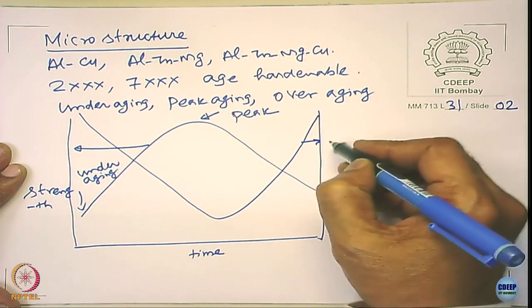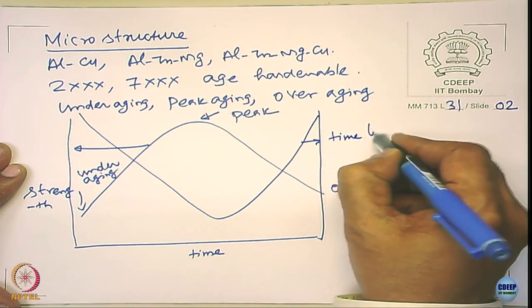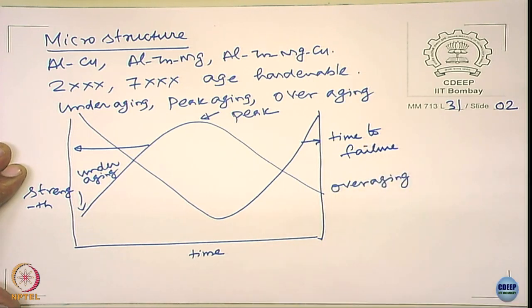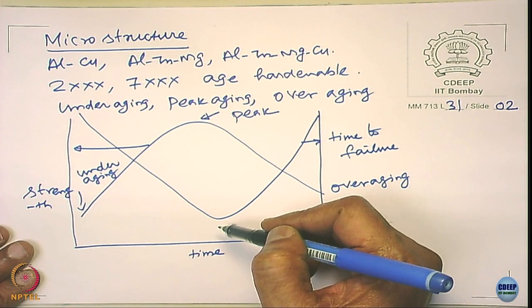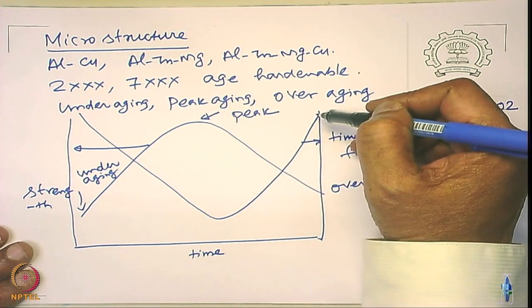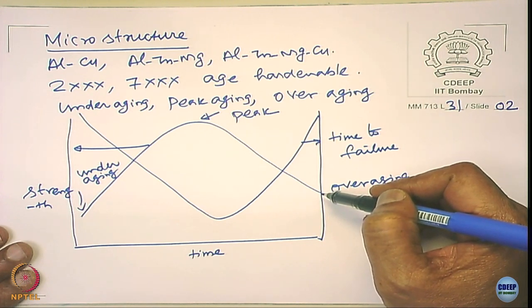At the peak-aged condition, the alloy becomes most susceptible to SCC. When you do over-ageing, the SCC resistance increases. So when you increase SCC resistance by over-ageing, you have a drop in strength level. There is some compromise on the available strength for structural applications.